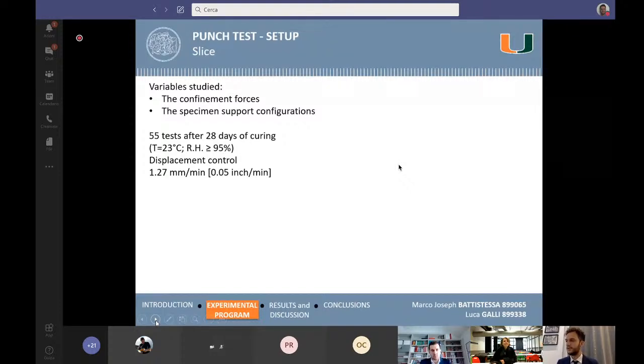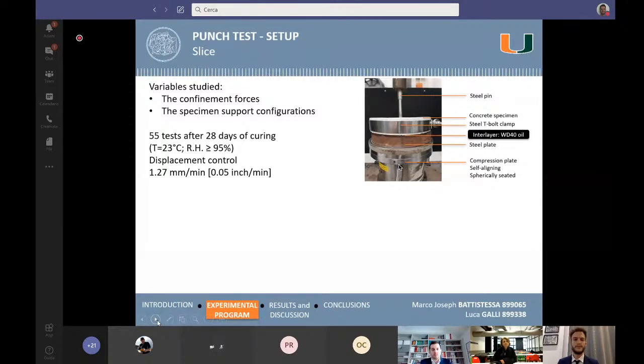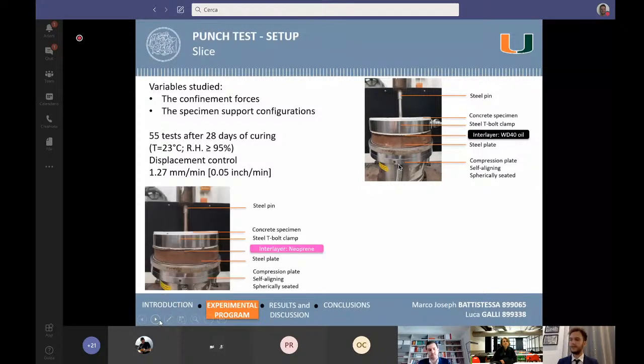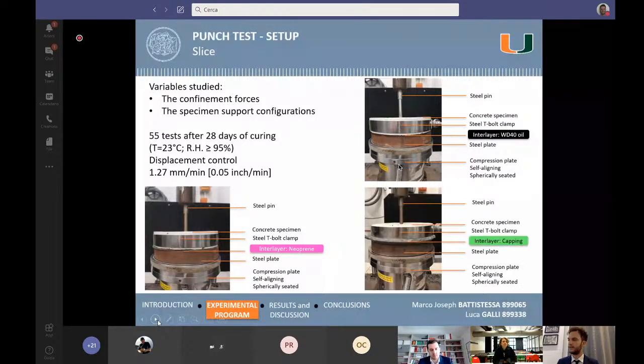To avoid that, we studied the effect of the confinement forces by applying a T-bolt steel clamp along the circumference of the slices in a range from 0 to 14 Nm, and also the specimen support configurations, where the differences were in the interlayer between the specimen and the support. In the first configuration, we used an interlayer of WD-40 oil to reduce the friction coefficient between the concrete and the steel plate. Then we tried a neoprene mat, 1.5 mm thick, and a third configuration, in which we applied a sulfur mortar capping on the bottom surface of the concrete. Of course, in these last two configurations, there is a hole in the middle of the interlayer to allow the rebar displacement.